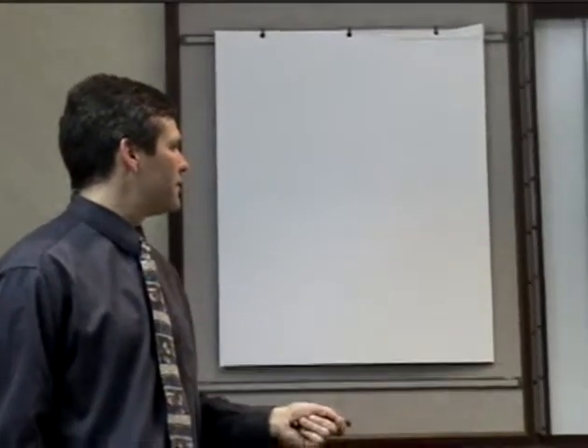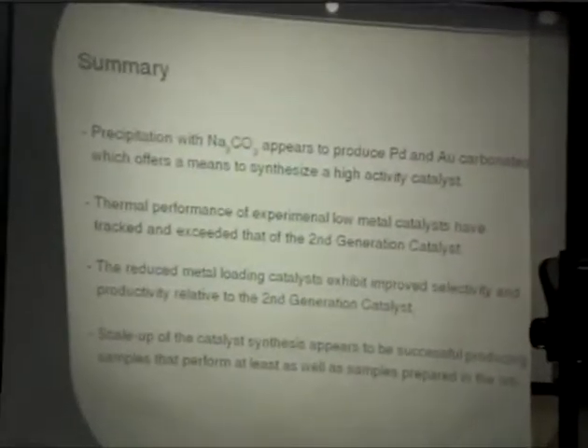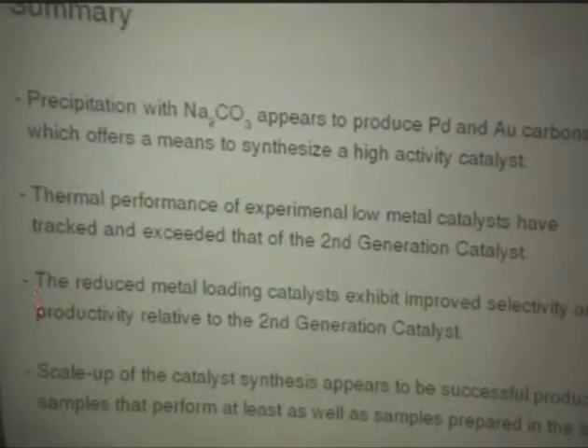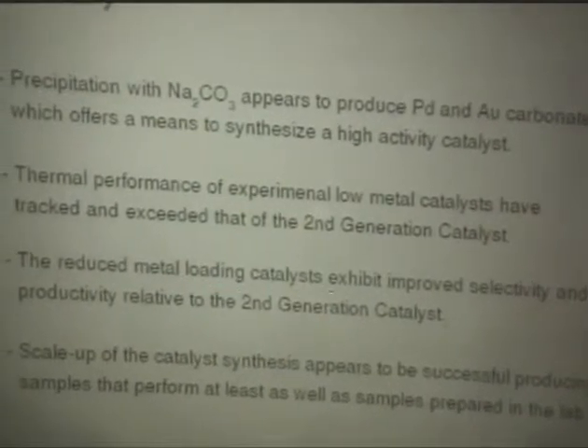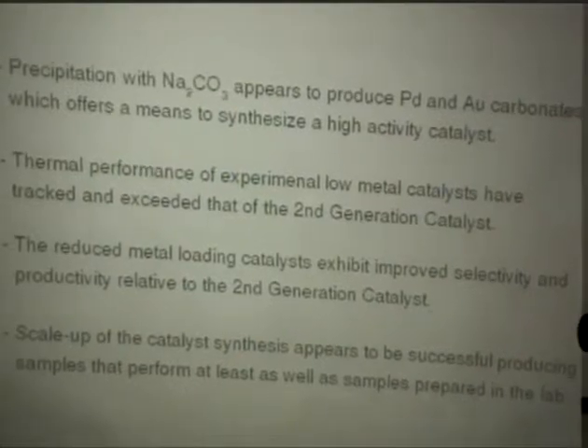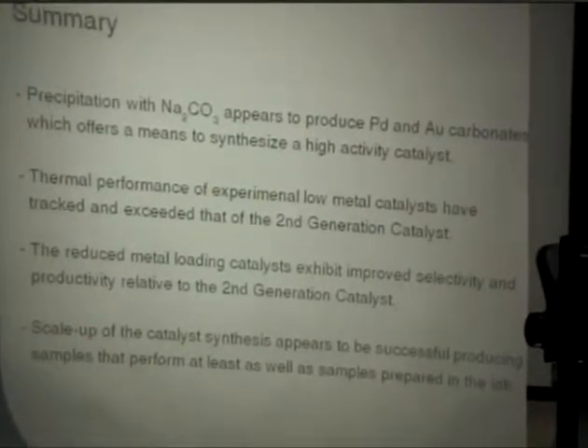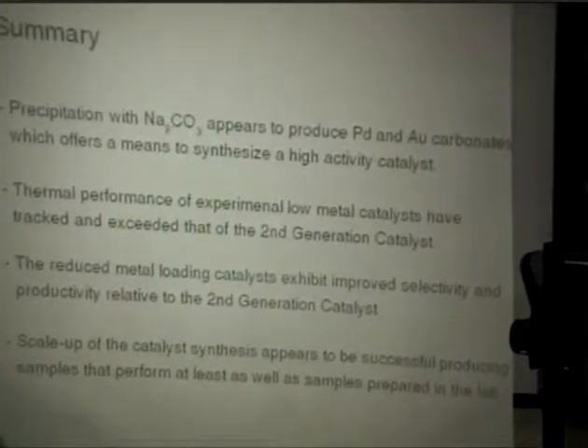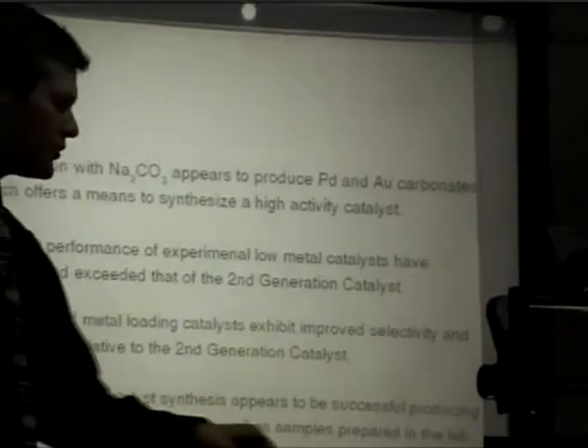As we've scaled that up and we've looked at the performance in our plant, the thermal performance of these experimental catalysts tracked and appeared to have exceeded that of our second generation catalyst. As we've scaled up, the reduced metal loading catalysts exhibit improved selectivity and productivity, and the scale-up has been very, very successful. So with that, I will finish and answer any questions that I can.